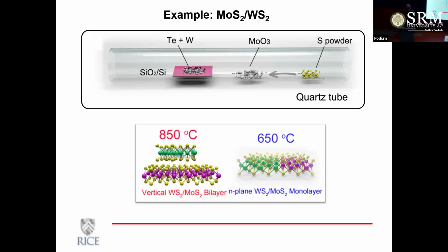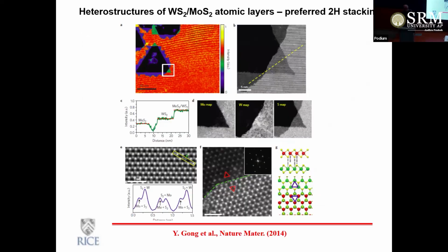And then to understand the properties, then to control the phases, then to control the twisting, right? All kinds of interesting things. And again, you'll be seeing a bunch of images. You don't have to really worry about the details. But what was possible from our experiments in the early days was that we were able to lock in a certain type of stacking in a certain window of growth synthesis parameters. So that was very good. At least we can create a heterostructure with a particular type of stacking, with a particular type of composition.